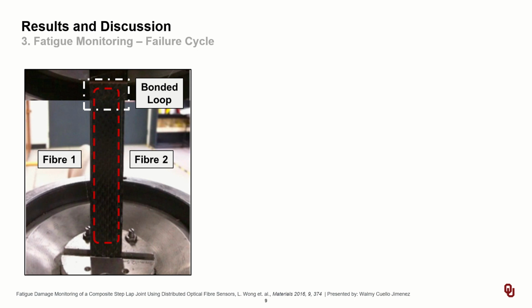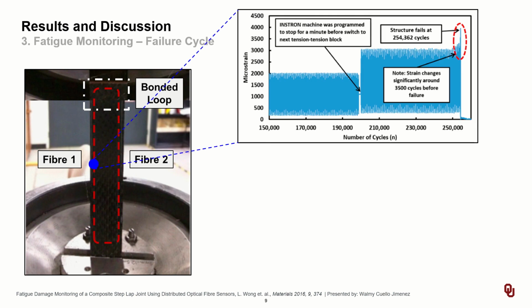Once it is proven that the system can measure distributed strain along the fiber, the focus turns to monitoring fatigue and ultimately the path to the failure point of the system. The strain was monitored again at the midpoint of fiber 1. The entire fatigue test was conducted for about 14 hours.